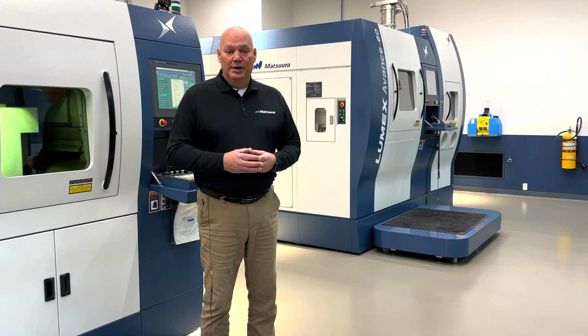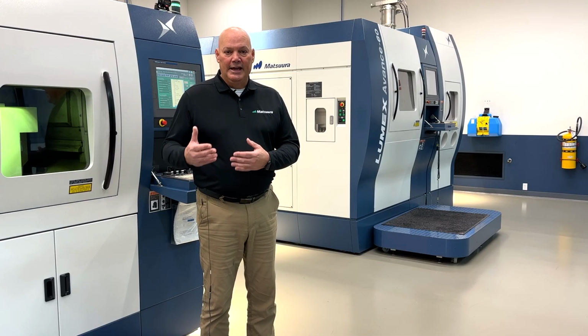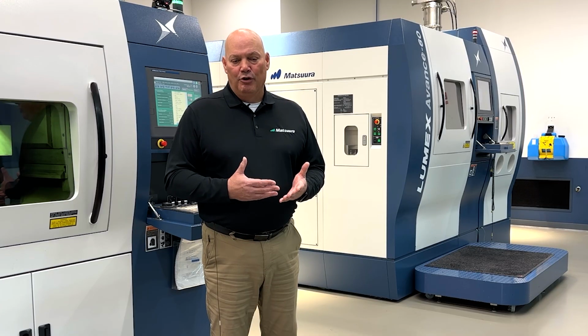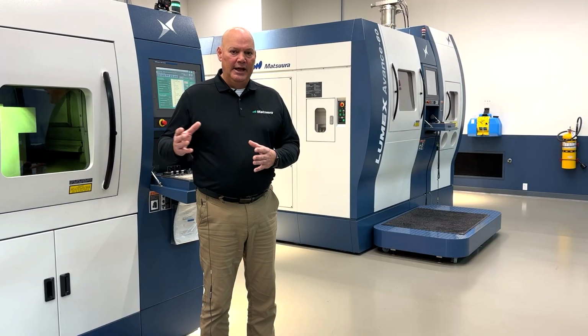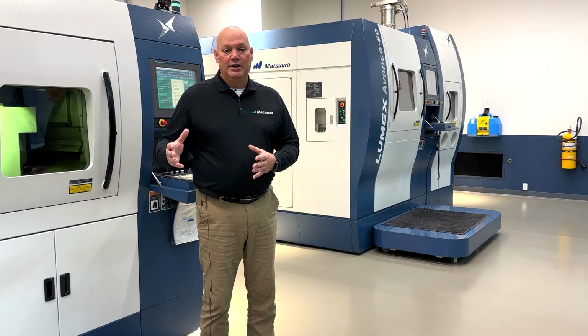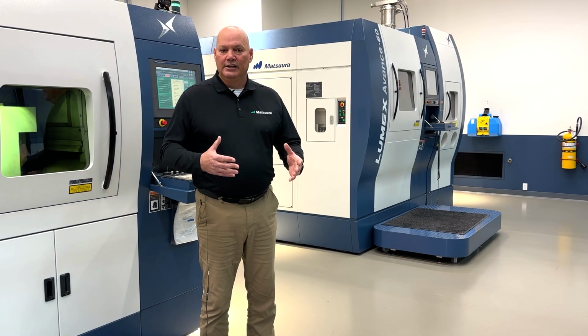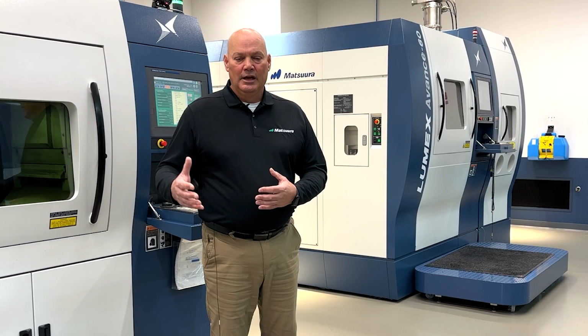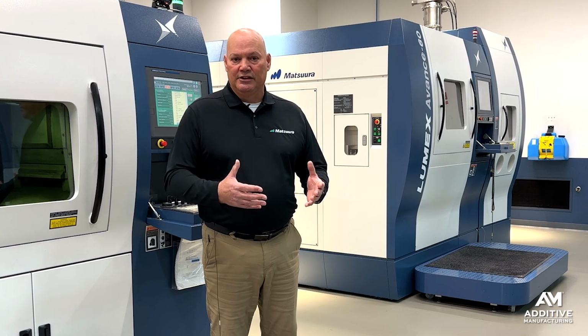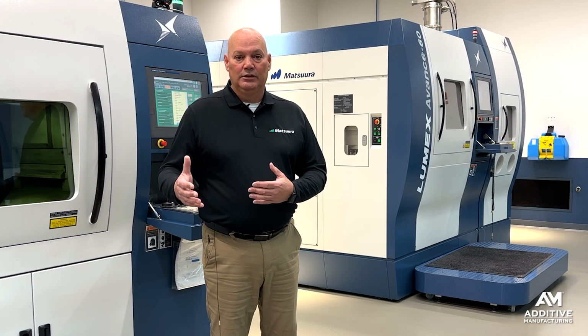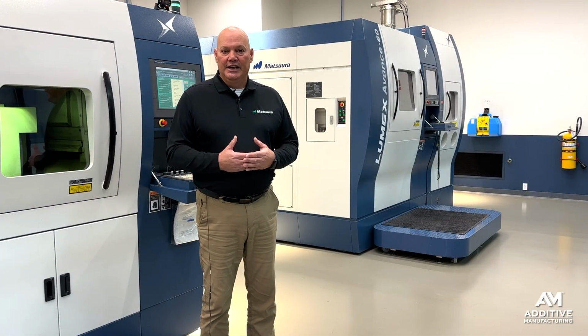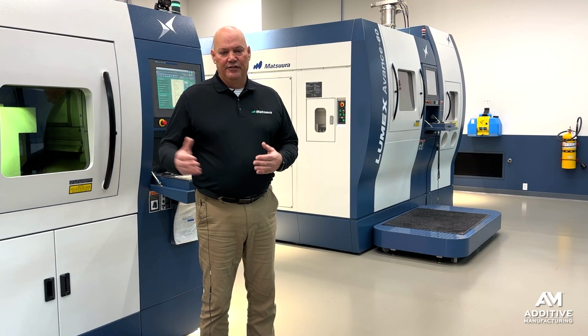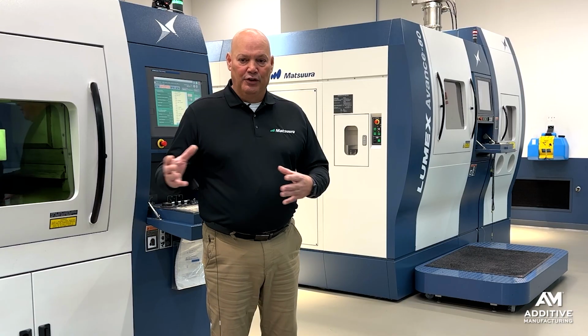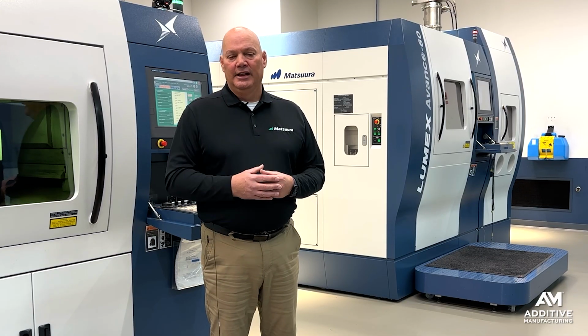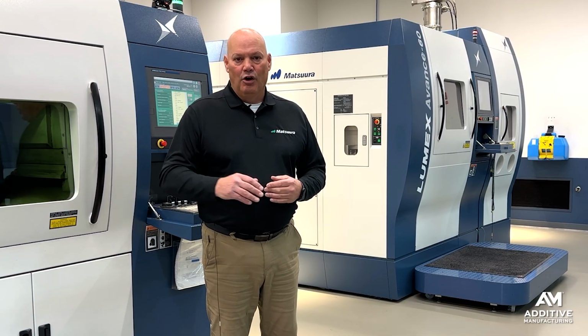So the cycle time improvement was significant. We went from a 28-second cycle down to about 14.5-second cycle. They were planning to build 32 cavity molds and a couple of them and dedicate 2 machines to them to meet the volume. Because we were able to achieve the cycle time, we were able to build 2 16 cavity tools. If you figure $150 an hour over 20 million pieces annually, that's a significant number. It's not yet fully defined, but the customer is estimating they saved about $5 million in capital over the life of the product.